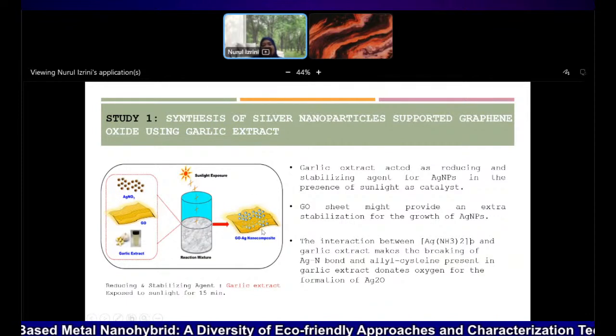In this case, the GO sheets might provide extra stabilization for the growth of Ag nanoparticles because of the unique properties of GO. It can anchor the particles and avoid agglomeration. Also, the interaction between the Ag-ammonia complex and the garlic extract causes the breaking of the Ag-N bond, and allyl cysteine present in garlic extract donates oxygen for the formation of Ag2O.